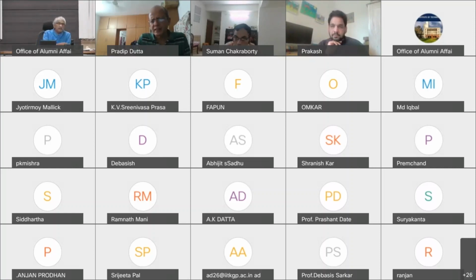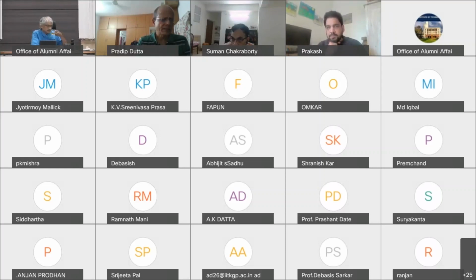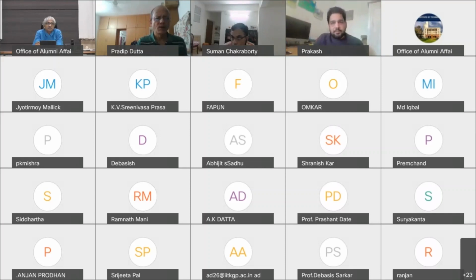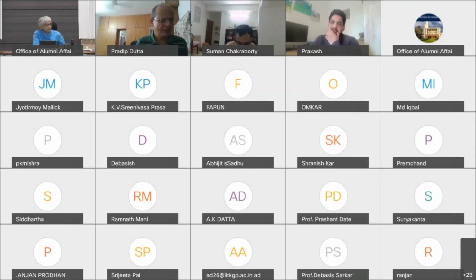The reason is that this viscosity measurement work we have done elaborately in collaboration with CMERI. My ex-student Prasenjit Das is there, and they have done extensive work on this. That is rheological studies. The important thing here is how to maintain the solid fraction. You have the solid fraction, you have shear rate, you have temperature also, because solid fraction and temperature are related. And the same solid fraction may be there, but the morphologies of the solid particles may be different. As you hold anything isothermally, the morphologies can change. So these are factors which are very difficult to control.